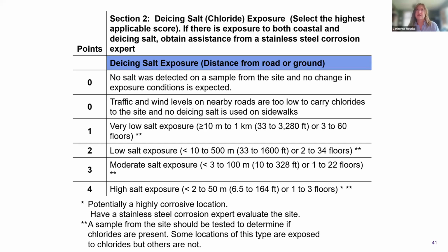And that's the map I showed you previously. De-icing salt is a bit harder to gauge in terms of how far it might travel. It really depends on the conditions. If you've created a canyon that happens to be lined up with a primary wind direction, how much salt is used. Generally, the highest salt exposure is on the first 3 floors. Sometimes it's just a few feet. It really depends on the specific setting. So evaluating the site is important. If you talk to the cleaning contractors for a given city, they generally will know how high salt goes on buildings in an area. And I should note that 70% of the United States has some de-icing.